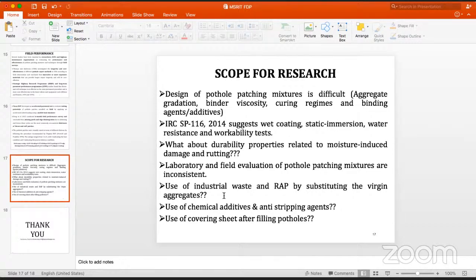If we come to industrial waste, as I told you, like steel slag, Kandal sir has done a lot of research on that, and they say that steel slag, may be LD, BOF, or EAF slag, the fine aggregates of this, below 4.75 mm, we can successfully use in the pavement construction. So we can use the steel slag or RAP in that. That is what I can tell, sir.